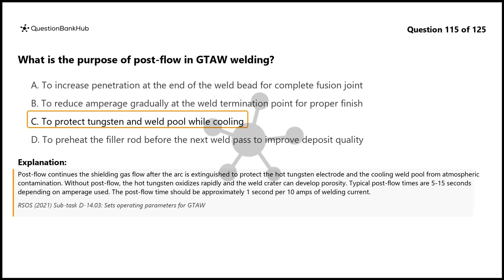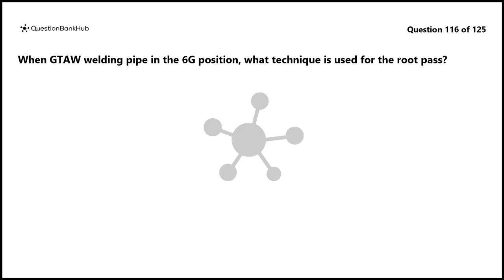Without post-flow, the hot tungsten oxidizes rapidly and the weld crater can develop porosity. Typical post-flow times are 5 to 15 seconds depending on amperage used. The post-flow time should be approximately 1 second per 10 amps of welding current. Question 116. When GTAW welding pipe in the 6G position, what technique is used for the root pass?